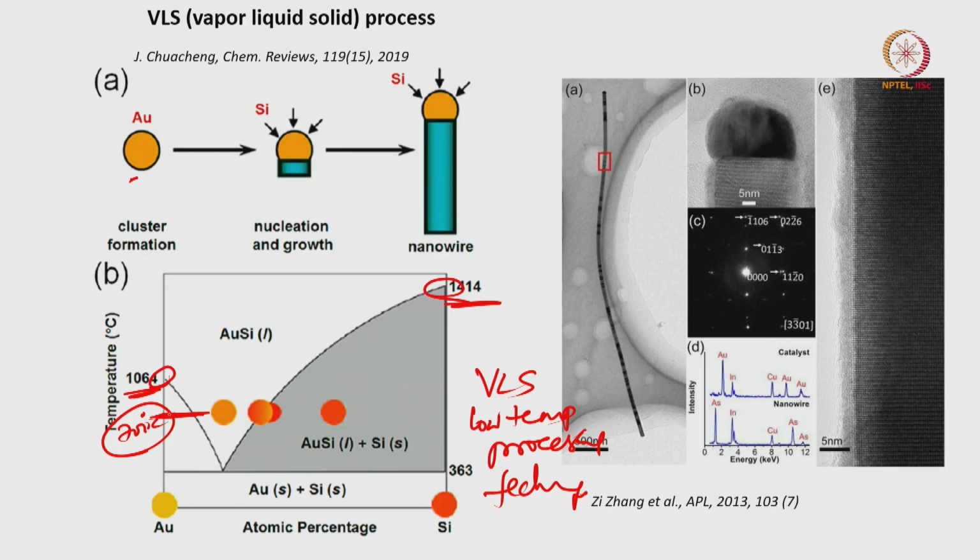Okay. Now at this temperature I start with pure gold, right. So gold is solid to start with; I have sprinkled solid gold particles. Then I am sending more and more silicon, and then you can see in this phase diagram, right, this is the eutectic phase diagram.